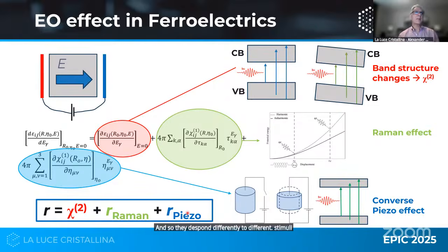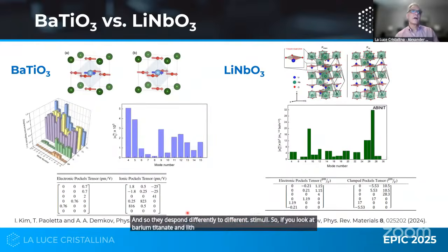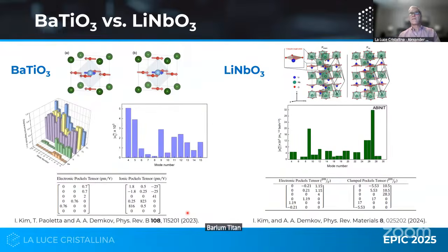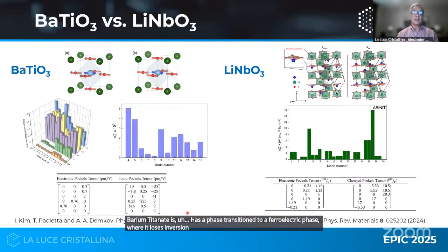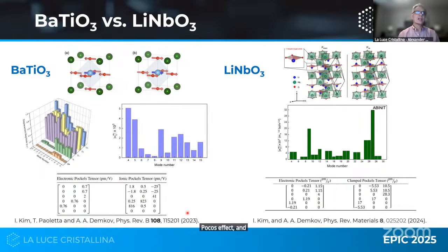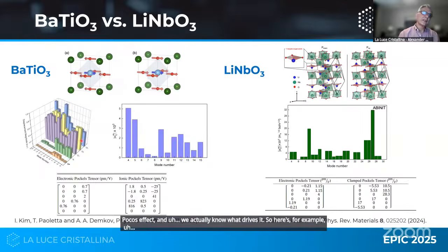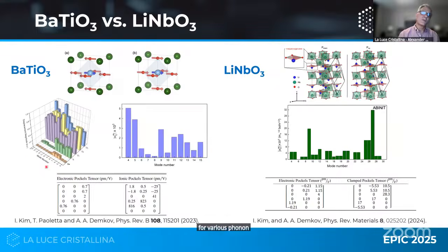So if you look at barium titanate and lithium niobate, barium titanate has a phase transition to a ferroelectric phase where it loses inversion symmetry, and that's where it gets the large Pockels effect. And we actually know what drives it. So here's, for example, the atomic displacement for various phonon modes, 15 modes of the unit cell, projected on every atom.